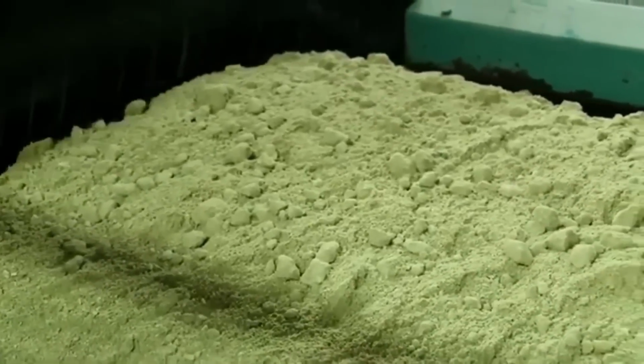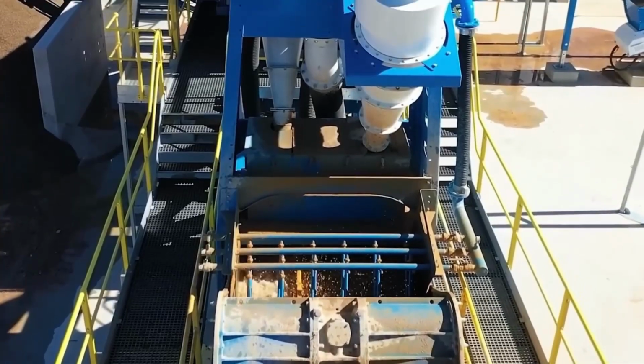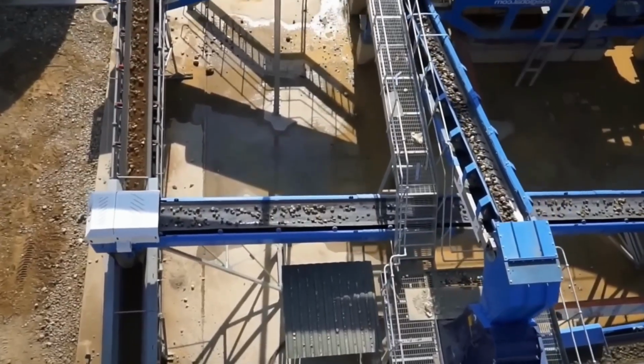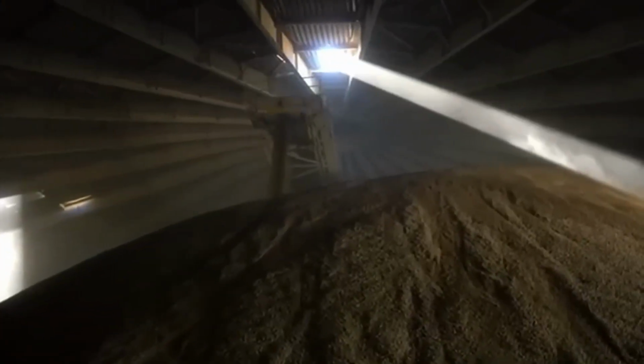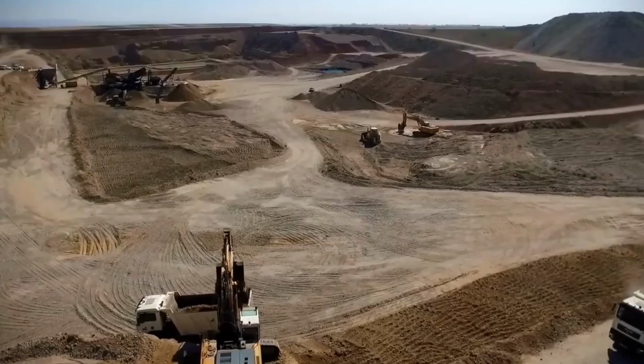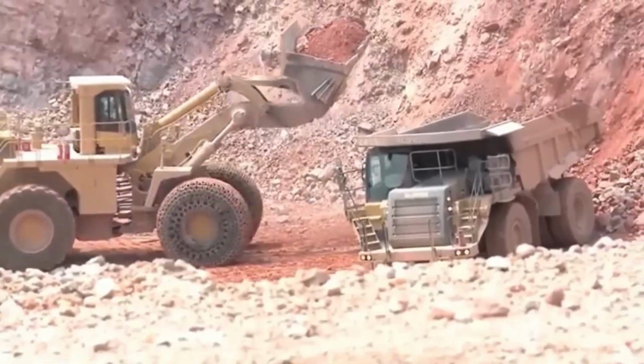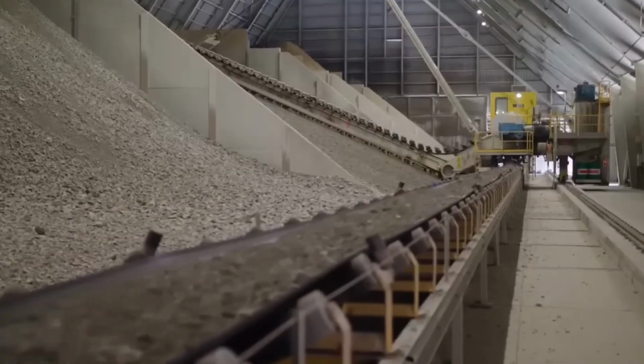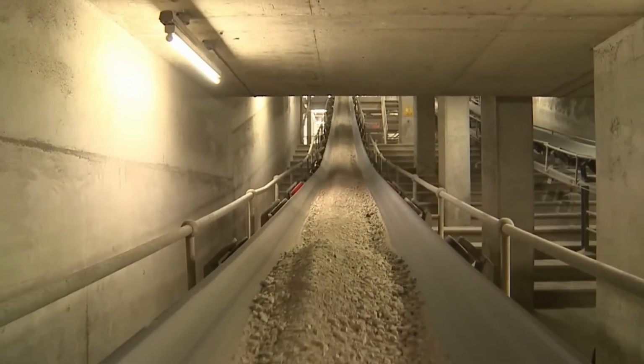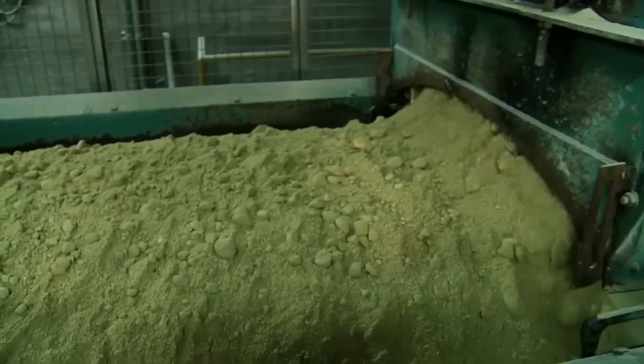This detail is vital. Any impurity, such as clay or iron, can ruin the transparency of the final glass. At the factory, more than 5,000 tons of sand are processed each week. To ensure a constant supply, trains and trucks arrive regularly from the mine. But before it can be used, the sand undergoes a thorough treatment. First, it is unloaded into giant hoppers that feed vibrating screens. These sieves filter out everything from large stones to the finest particles, starting with meshes of 30 holes per square inch. Next, it enters washing chambers, where powerful jets of water, driven by 200 horsepower pumps, clean the sand at an impressive rate, more than 220 tons per hour.